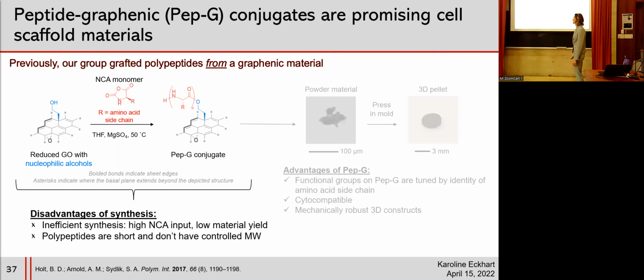But this synthesis had some drawbacks. For one thing, there was a relatively high input of NCA with a low output of material. And another issue with this is that the peptides were fairly short and there was no control over the molecular weight of the peptides. Because graphene oxide is a heterogeneous material, you don't actually know how many moles of initiating groups you're adding with respect to the monomer. So you don't have control over how long the peptides are or how many peptides there are.